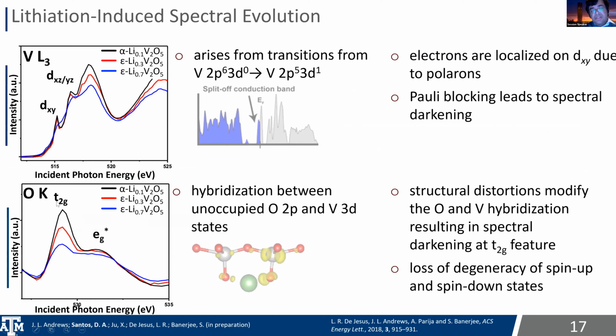Another signature of this, the oxygen K edge, is the change in relative intensities of the t2g and eg* states, and this is happening again because of structural distortions modifying the vanadium oxygen hybridization, but really from a lot of DFT modeling done in collaboration with the Prendergast group, it's because of the loss of degeneracy of spin up and spin down states once you go from a d0 to a d1 system. So we've got two ways to really identify very precisely the d electron density as once lithiations have started to happen.